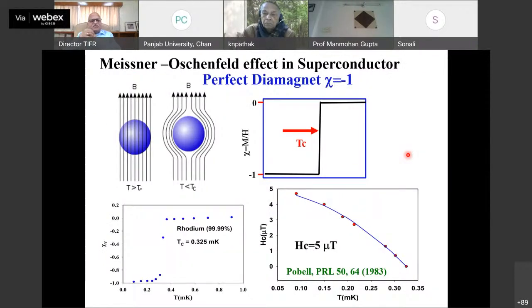So, as I said, how does one do the diamagnetism or discover the superconducting transition? At high temperatures, when you apply a field, the field penetrates, and then when it goes to a superconducting state, it expels the magnetic field. So if you measure the susceptibility as a function of temperature, you see a sharp drop, and that is the signature. So when you build a magnetometer, you have to check whether it works, and we did it with rhodium, which we see is at about 325 microkelvin. This was discovered by my mentor Frank Pobell, as I said, more than 40 years ago. And so our data matches with Pobell's data. So we are sure that our magnetometer is working very well.